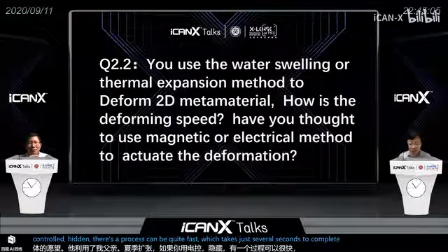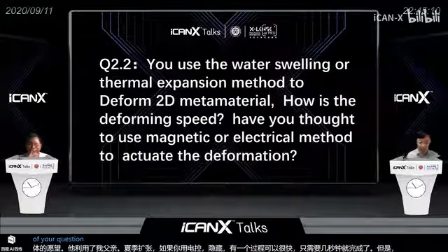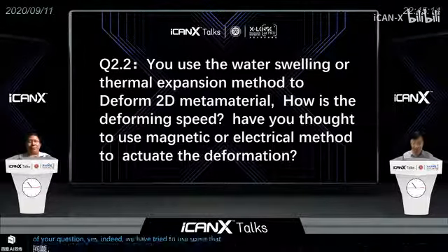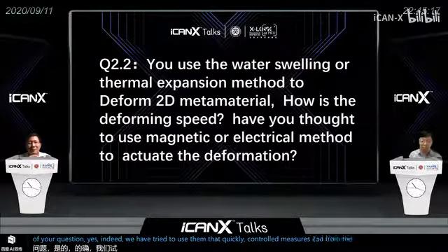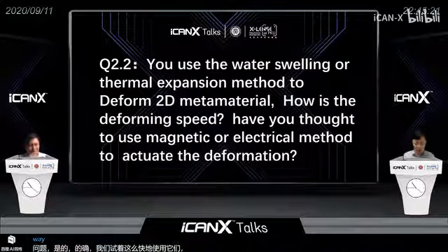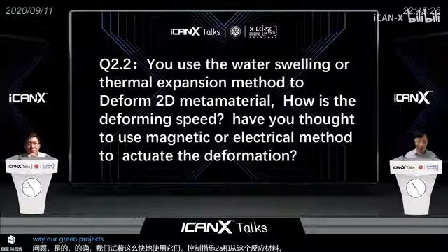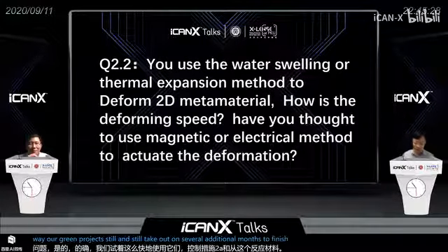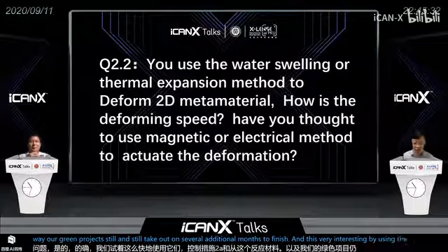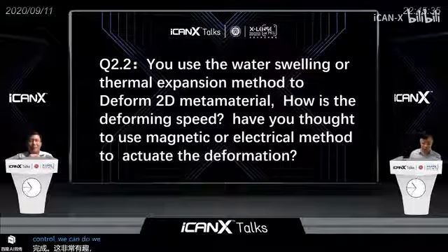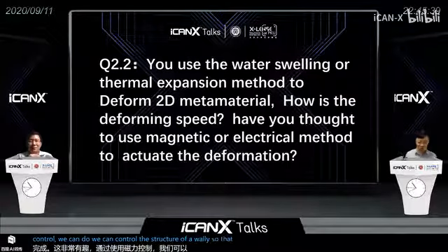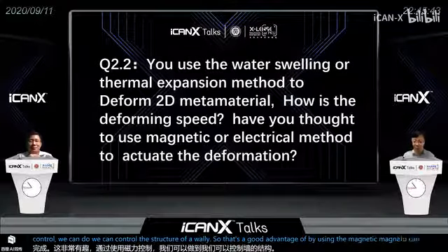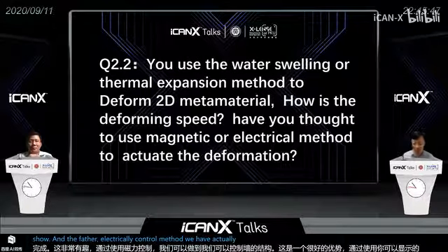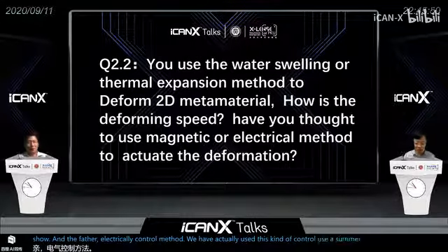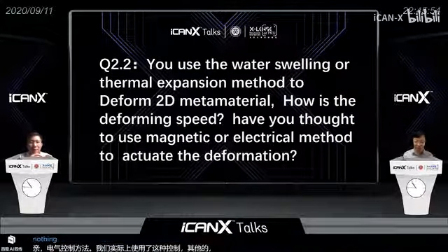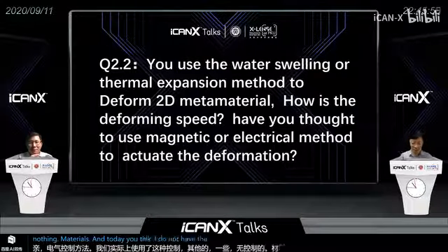And for the second point of your question, yes, indeed, we have tried to use some magnetically controlled methods to deform these responsive materials, and our ongoing projects still take several additional months to finish. And it's very interesting. By using the magnetic control, we can control the structure wirelessly. So that's a good advantage of magnetic control. And for the electrically controlled method, we have actually used this kind of control in the thermally controlled metamaterials. In today's talk, I did not have enough time to expand on that topic.